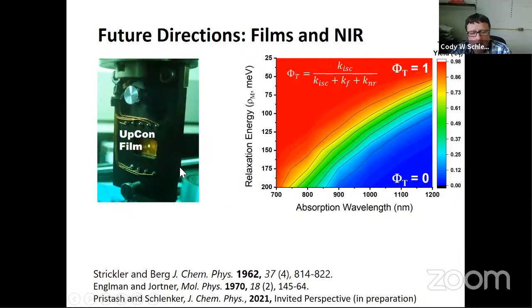Okay, so I pitched this idea that we can take heavy atom-free materials, and they may have some potential for solar energy applications. And then I showed you some red excitation, which is clearly above band gap for a cadmium telluride cell. What we've done now, and hopefully this paper will be coming out soon, is we've taken the photophysical parameters that we've collected from the kinetics measurements, and we've said, well, what does the energy gap law say about the rate constants for the non-radiative decay? What does the Strickler-Berg relationship say for the radiative rate constants? What have we measured for the intersystem crossing times? And what are some reasonable predictions that we might come to for this class of molecules if we were going to try to harvest photons that would be sub-gap for a cell like cadmium telluride?